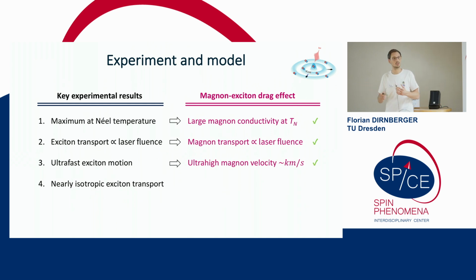It is also interesting to note that while the exciton motion should be fairly slow in this material, we do see very fast transport of the excitons, and if you play out the numbers, it actually matches quite well with the kilometers per second that have been reported for the propagation speed of the magnons in this material.